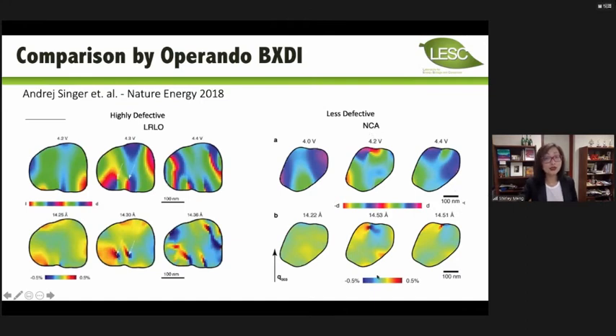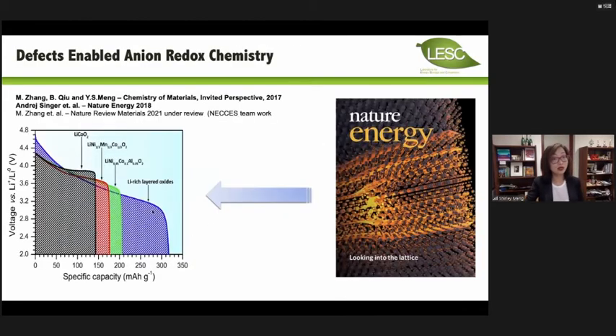So the classical materials and the new anion redox materials have completely different tolerance to the defects. And for material scientists, the question is whether the defects are good defects or bad defects. So if you have the defect density engineered correctly in the particle, it can indeed store more lithium and release more lithium reversibly and give you more energy density. So this kind of breakthrough in the energy density for the cathode materials is so exciting for us.